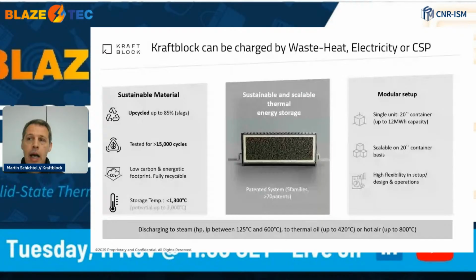Our storage material is a development by ourselves. We looked at chemical storages at that point in time. Well, too complex, too expensive. Phase change materials were also not in favor for us, because we want a storage that can operate in a whole broad temperature range rather than being focused on a special temperature segment. And also, of course, molten salt, right? Corrosion, system stability, degradation. It was quite early stage for those materials when we started. So we stayed with sensible storage materials. We are using mainly upcycled or recycled materials, for example steel slag, waste of bauxite production, waste of copper production, combine them with a special type of binder that we developed, and then just put it into the storage device. Storage temperature, I said it at the beginning, maximum 1300 degrees C at the moment.